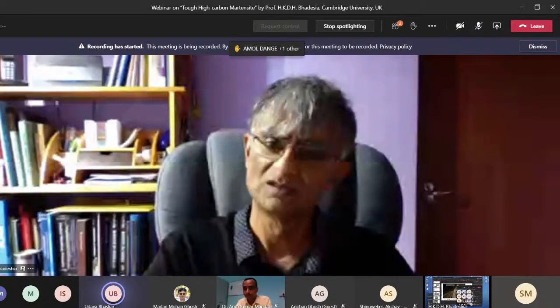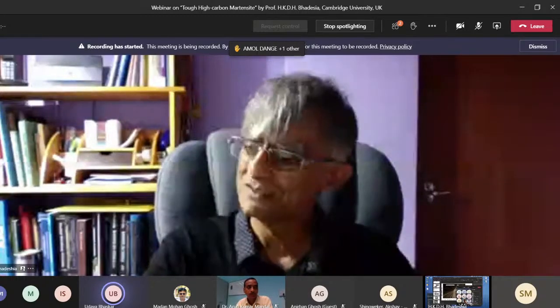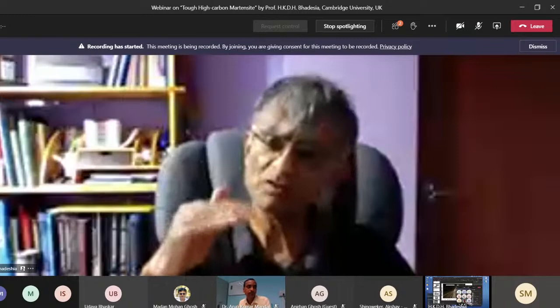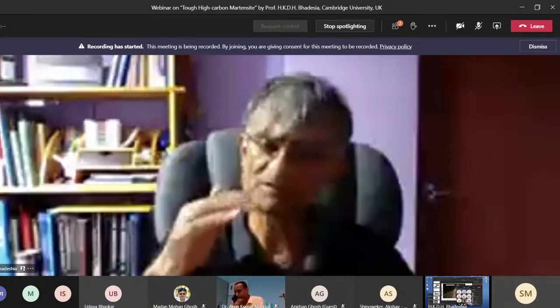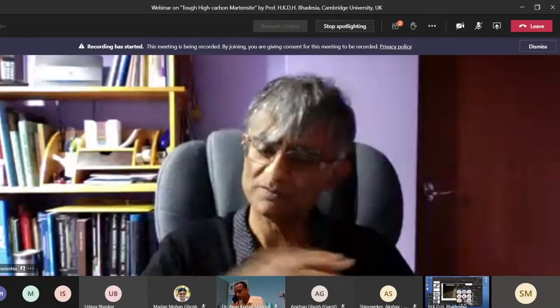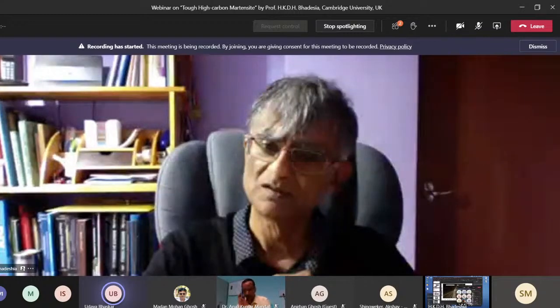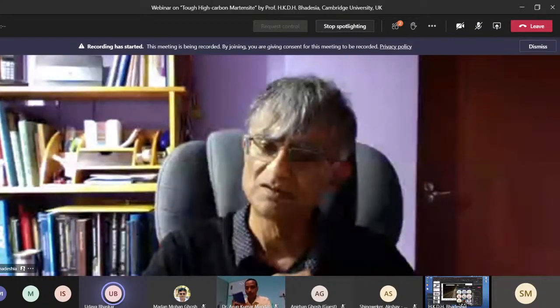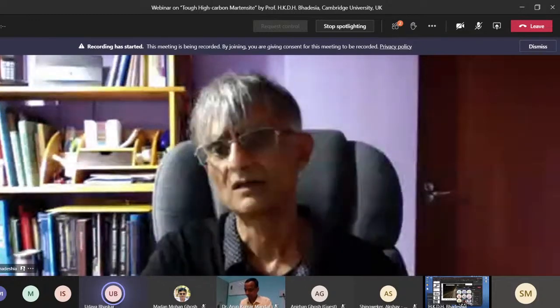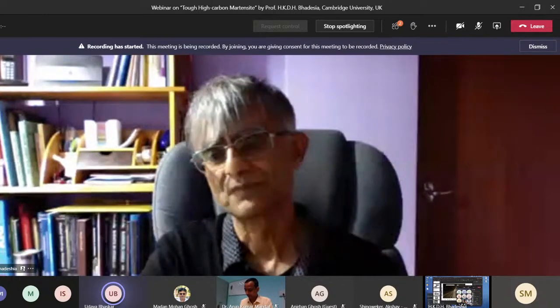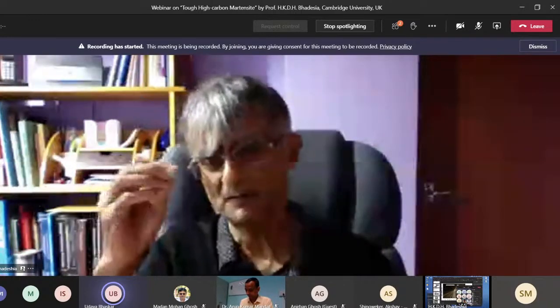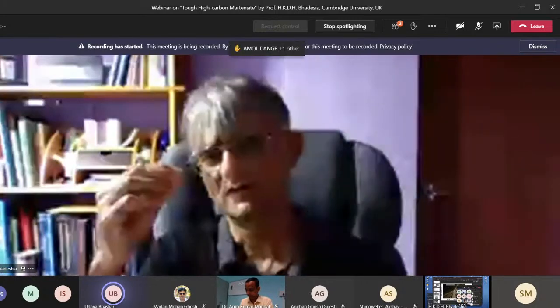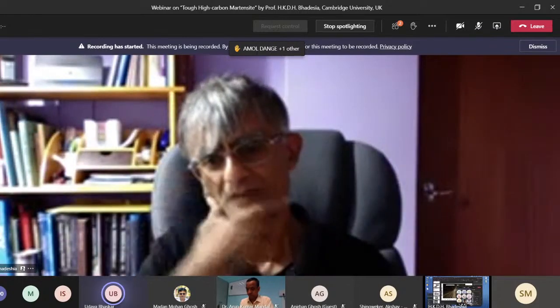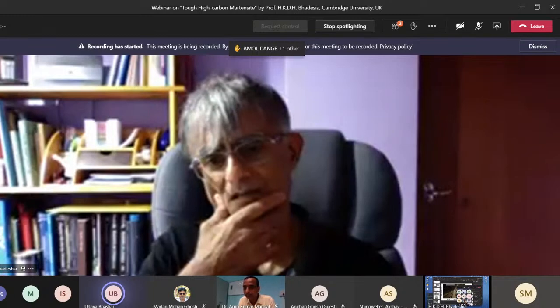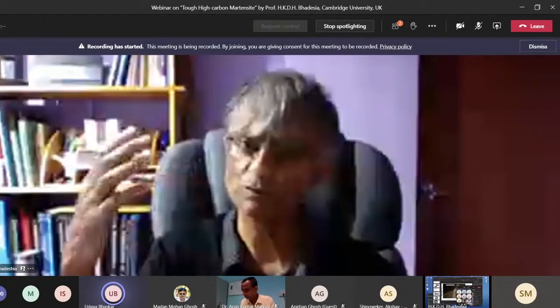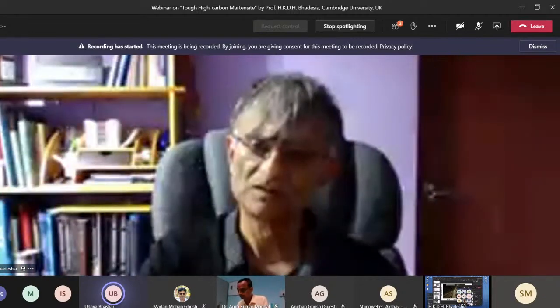But what is the reduction ratio you're looking at, sir? Oh gosh. From memory, I can't remember, but I think the ingot itself must be about 4 centimeters high, and we've gone down to about 6 millimeters. Okay, because if I want to try the same steel in my components, I need a really big ingot size and reduce it to smaller sizes. I think it's the final step that's really important to get that pancake structure. Okay, and that is happening only because of forming. Am I correct? Yeah, because of the low finish rolling temperature. Oh, okay. Thank you, sir.